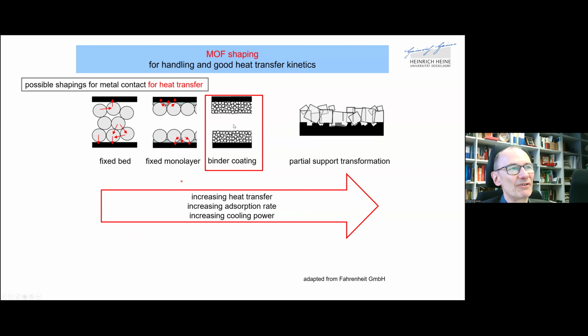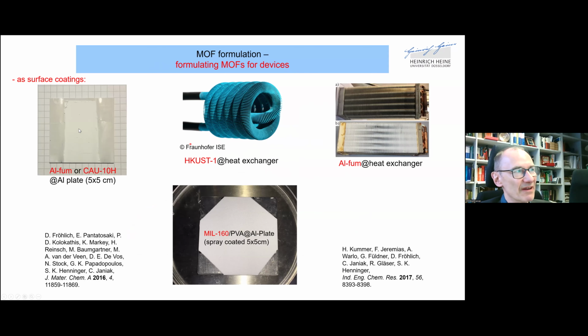So let's go down to the binder coating, which is more efficient and also a bit more complicated. For that process, we could use a surface coating process, a spray coating process, or a dip coating process. For the actual example, we used the dip coating process, where this heat exchanger was dipped with slurry, which contained the MOF.